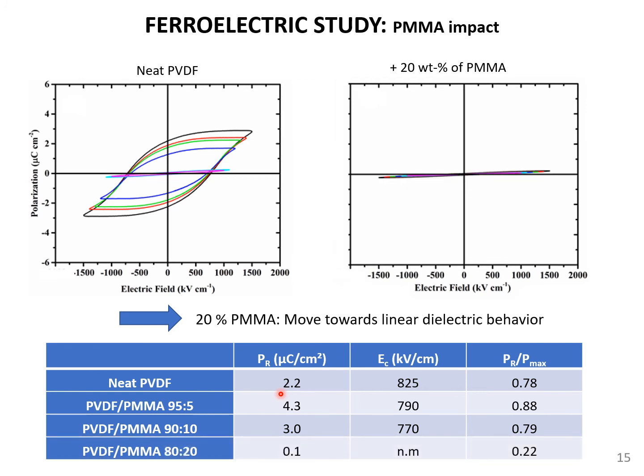And this is particularly true when you add 20% of PMMA, where you observe no piezo or ferroelectric behavior, indicating that you have more or less a dielectric behavior in this case.